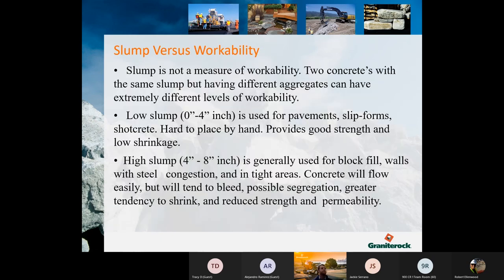However, slump is not always a measure of workability, although it's an indication. Two concretes with the same slump can have different aggregates and extremely different levels of workability. Like I talked about, a low slump is 0 to 4 inches. It's mostly used for pavements, slip forms, shotcrete. It's hard to place by hand, but it does give a good strength with low shrinkage.